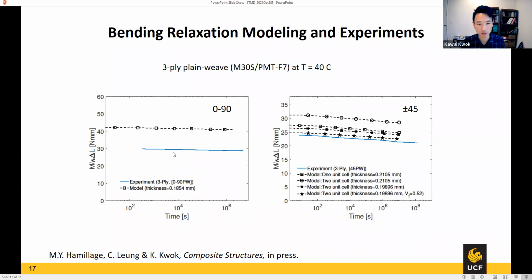The experimental data is down here, and you see that the model has quite a bit of overprediction when compared with the experiment. We tried to figure that out for quite a bit, and we see that on most of the tests we have done. One of the reasons we think there is such a large disagreement is the fiber: our assumption of linear elasticity and symmetric tension and compression properties is not a very good assumption.